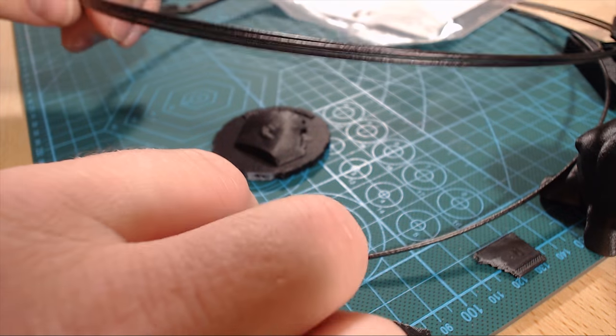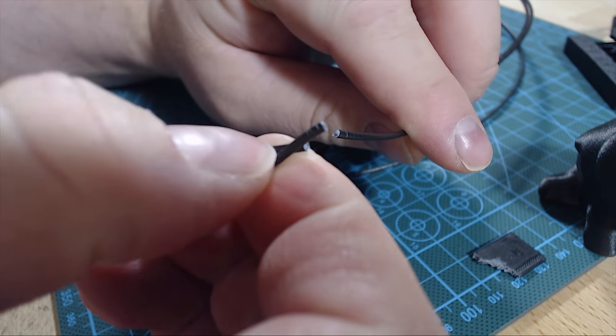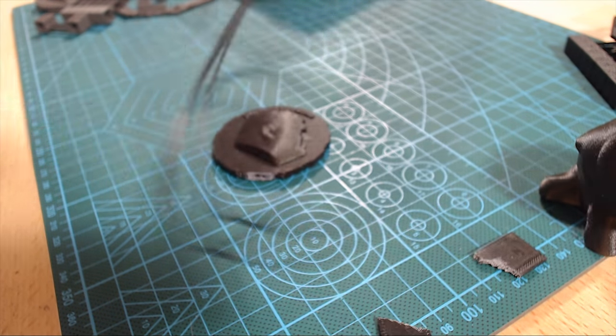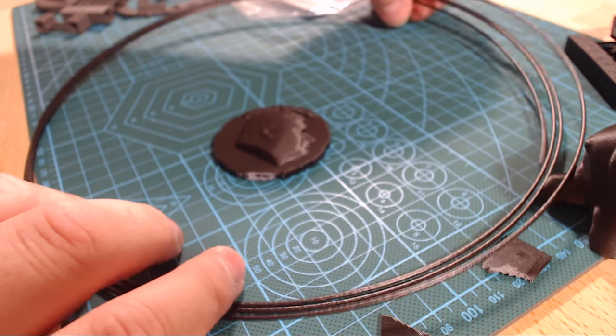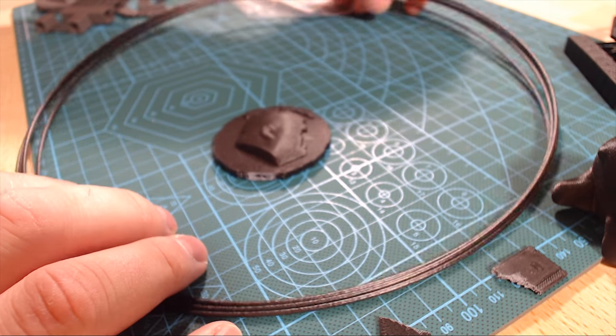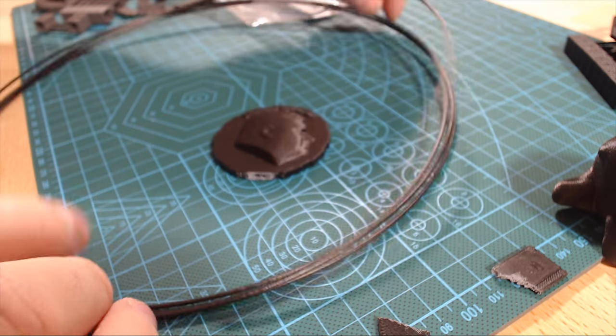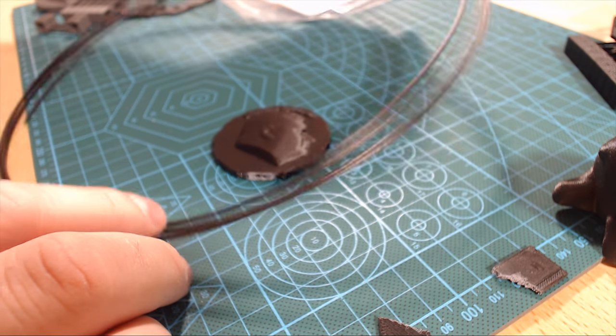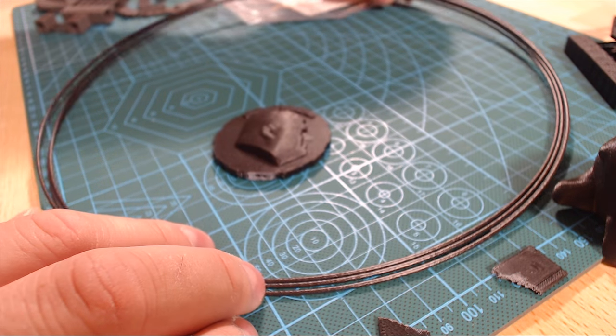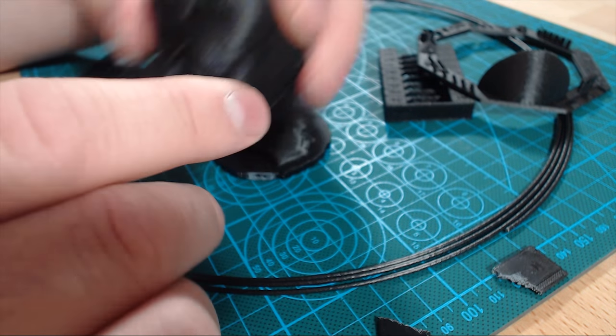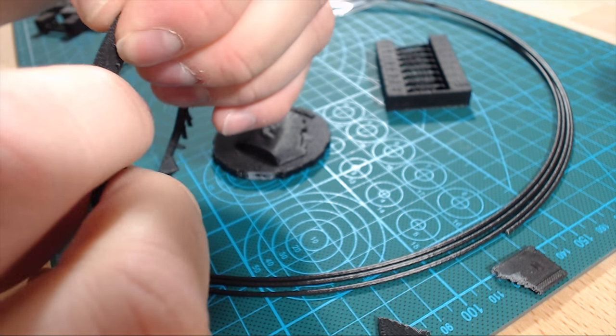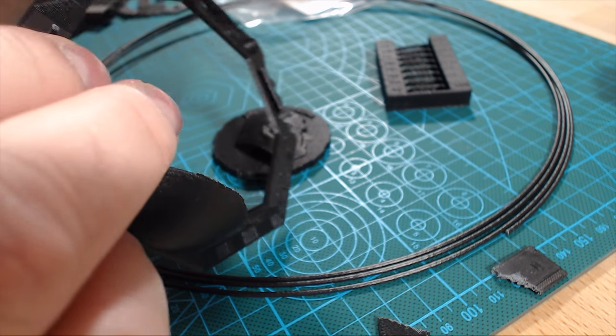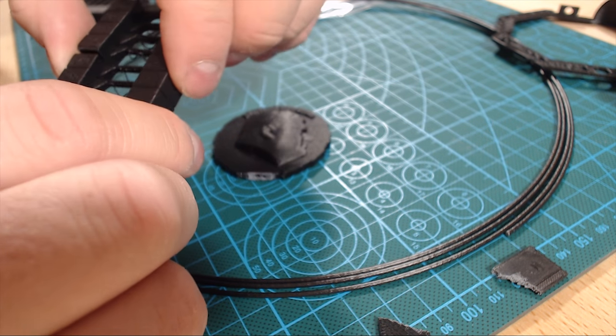The filament itself before printing is very brittle. You have to be careful handling the filament. And when I took it out of the bag it coiled up in a very big size coil. And I tried to put it on a normal spool and broke this part off just by bending it too much on the spool. So you have to handle it with care this filament and not bend it too much on the spool. But other than that the print quality is great and I'm really happy with the filament. And it's quite stiff. It's more stiffer than normal ABS. But I think this is a great filament for an ABS filament.